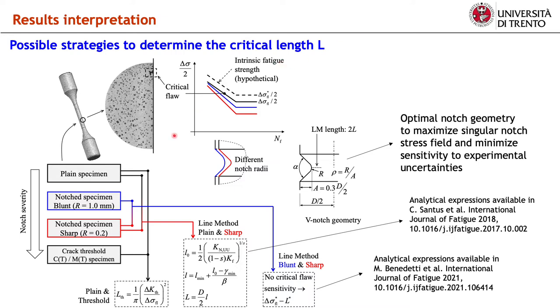Specifically, we term "plain and threshold" the approach based on the determination of L starting from plain fatigue strength and crack threshold, delta K_TH. With "plain and sharp," we denote the inverse search method recently derived by us in this paper, based on the use of a plain sample and a notch sample with optimal shape to minimize the sensitivity to experimental uncertainty.